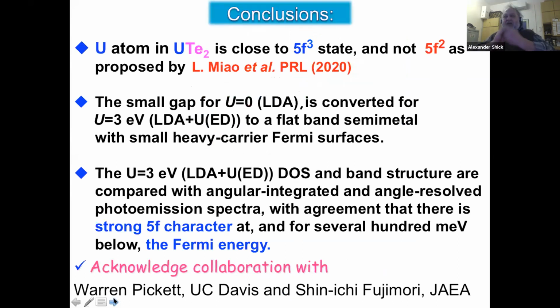All right, so then I come to the conclusions. The first thing is that uranium in uranium ditelluride seems to be close to the 5f3 state and not 5f2, as was proposed from the measurements of Miao and the corresponding theoretical analysis. And when you consider the correlations, then your band structure turns from a narrow band semiconductor to a flat band semi-metal. And our calculations provide good quantitative agreement with both angular integrated and angular resolved